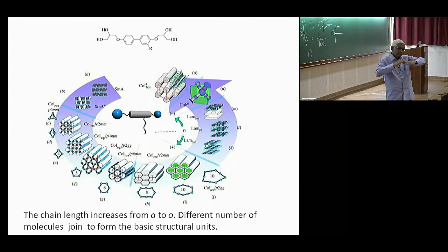To avoid that, you have a pre-tilt, as it is called, 2 or 3 degrees. And these particular polymers are supposed to give you 2 to 3 degree pre-tilt when you rub it with some force. So I think it's a pretty sophisticated technology from the technological point of view.